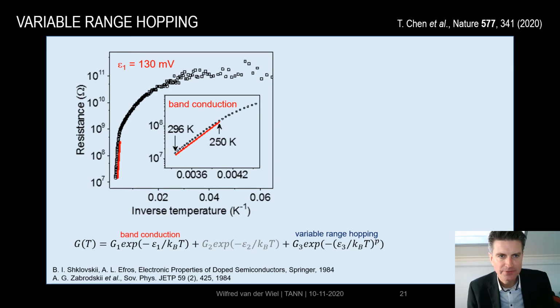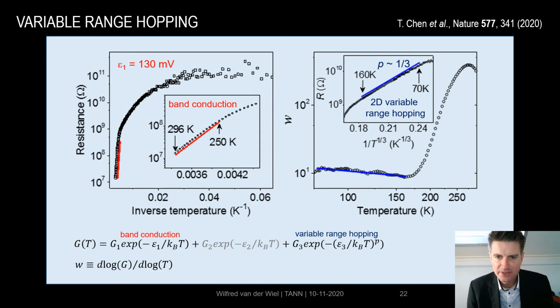A little bit more on the physics of variable range hopping. Here we map out the resistance versus inverse temperature, and this is the general expression for the conduction. So we see that at relatively high temperature, so from about 250 K and up, we basically are in the band conduction regime. That is typically the regime in which conventional devices such as transistors are being used. However, if we go to lower temperature, and the data is plotted a slightly different way, but for now it doesn't really matter, we see that for a region about 100 Kelvin, between 70 K and 160 K, we are in the so-called variable range hopping regime.